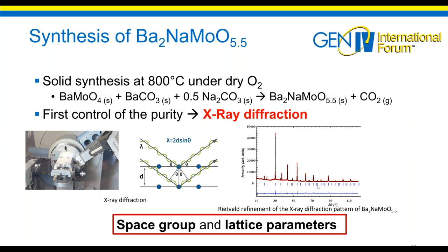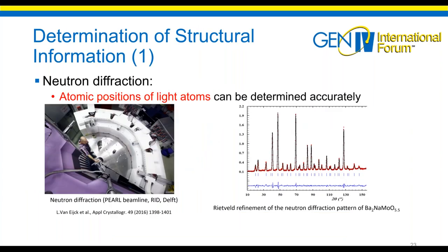As we can see here, we cannot see any additional peaks. Therefore, the compound was really pure. And then we also performed some neutron diffraction measurements. The neutron diffraction principle is exactly the same as X-ray diffraction, but you are using neutrons instead of X-rays. Therefore, the neutrons will be scattered by the atomic nuclei and not by the electronic density surrounding the nucleus. Thanks to that, you can really see the atomic positions of the light atoms.